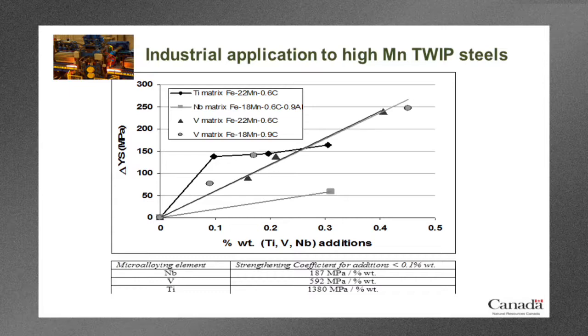And that's because essentially all of the titanium is coming out during the solidification. There's a big blocky TiN, and it doesn't add to any strength. So you really can't exploit the potential of titanium in these steels. The grey square at the bottom is niobium, where we tried to add a bit over 0.3 weight% niobium. What we found was that we did get quite a lot of precipitation, but the precipitates tended to be very big, about 30 nanometers in diameter. And so they're not very effective as strengtheners. We tried various heat treatments, various types of recrystallization annealing, cooling. We couldn't really do anything about that. So it seems to be ineffective for strengthening.